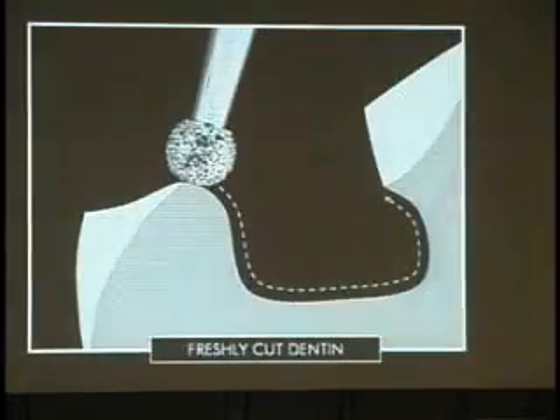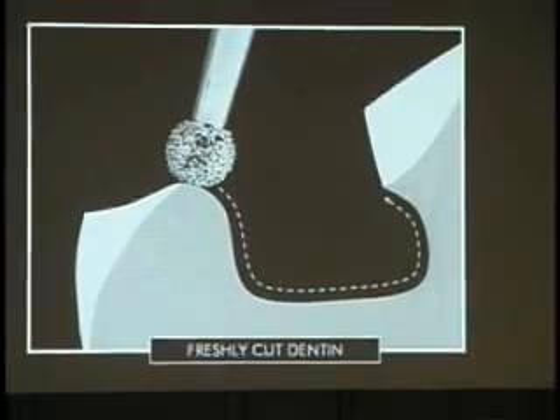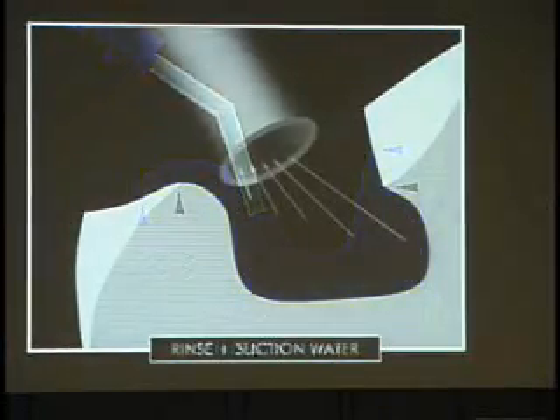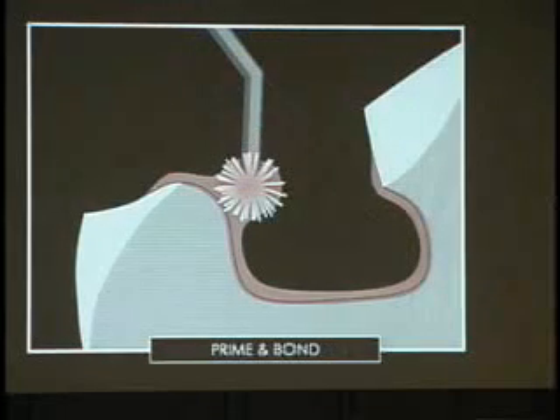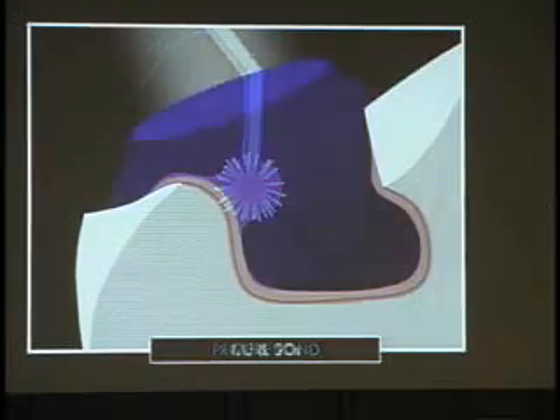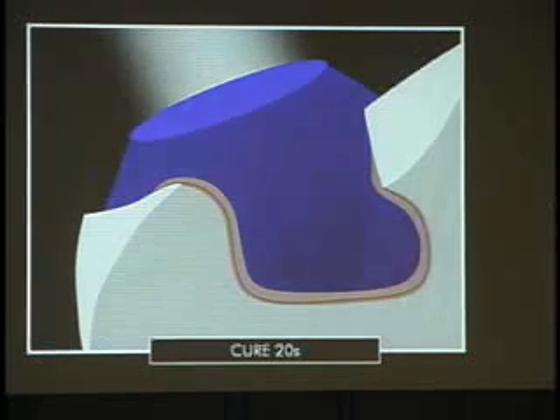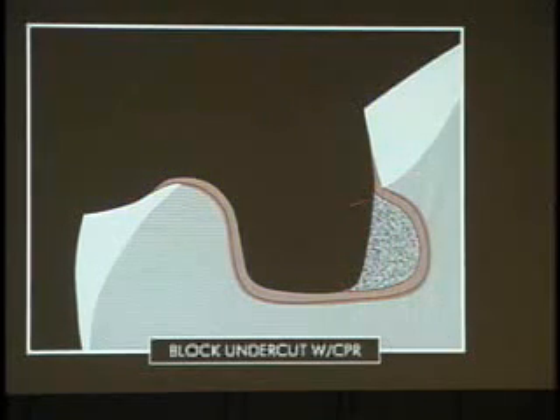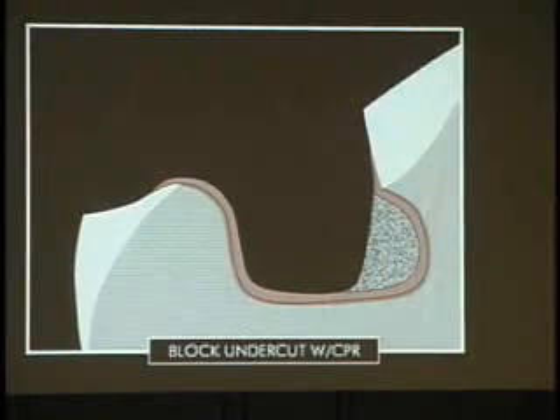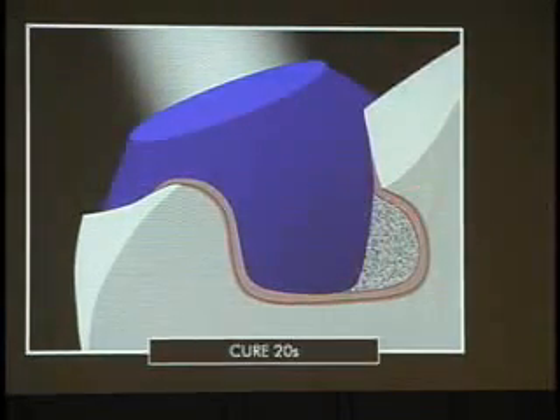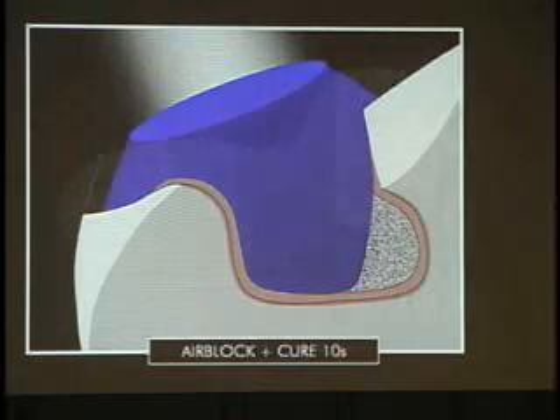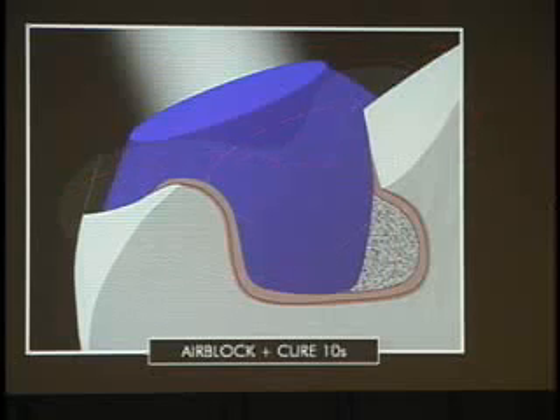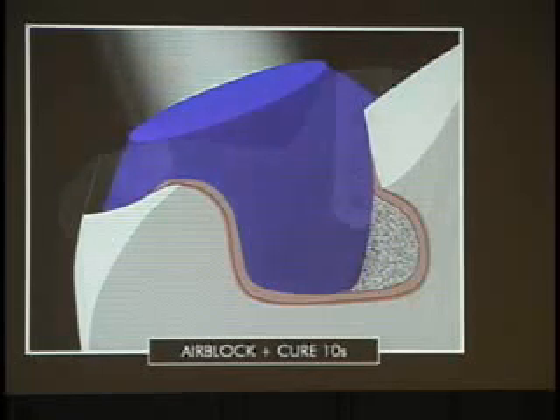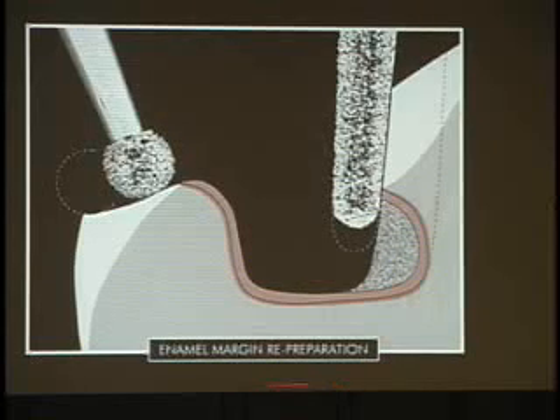So really what is recommended today is when you are done with your preparation for your indirect, you freshly cut dentin, you etch, you prime and bond. You suction the excess of water always before you use your prime and bond, you never blow air to avoid the collapse of the collagen, and then you cure the adhesive, very important. You take advantage of the process to block maybe some undercuts because of these existing cavities, and then you cure the composite that you use for blocking the undercuts. You air block with glycerin jelly and cure again to avoid the inhibition layer on your adhesive, and then you just clean the margin and you are ready to take your impression. And you do that before taking the impression.